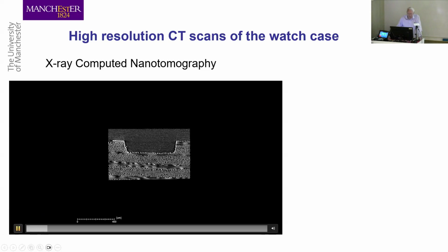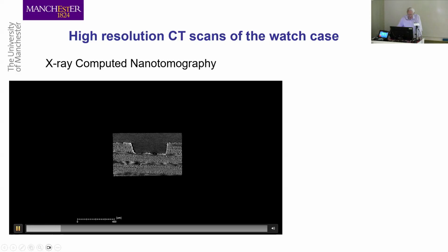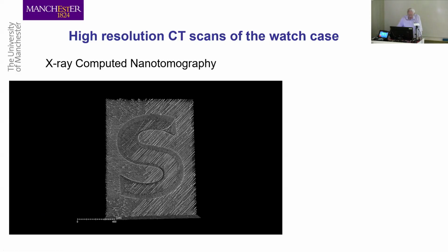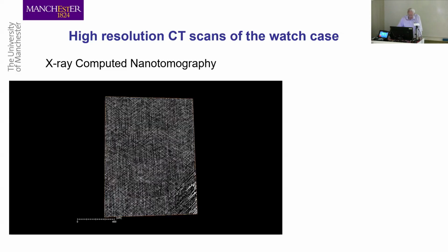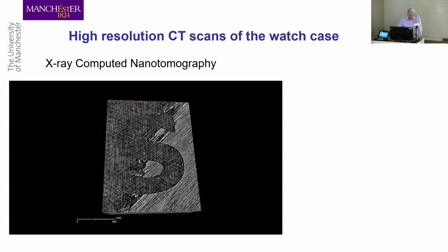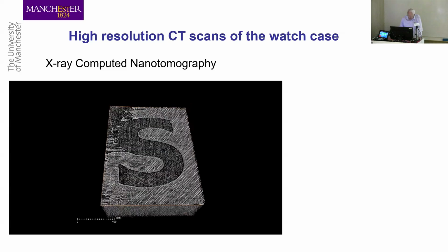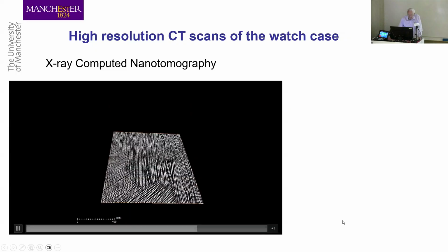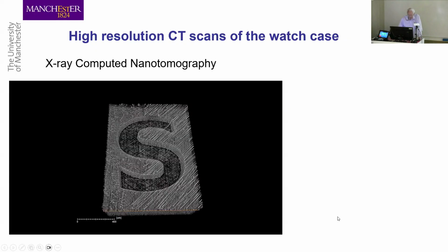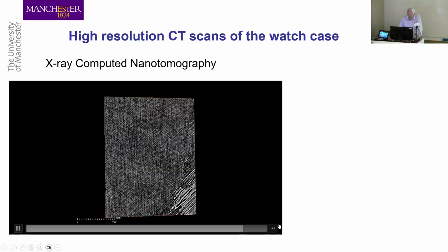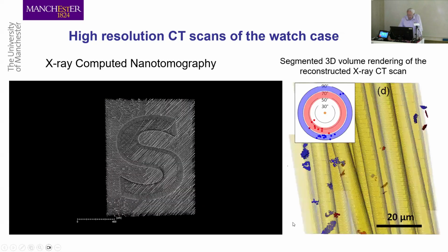It's an S because it's Swiss made. This company is a Swiss watchmaker. And this is a carbon fiber case of the watch, which we started with. We then impregnated it with graphene into the matrix of the resin. And you'll see here, this is again some CT scans showing the carbon fibers now with the graphene flakes around them.